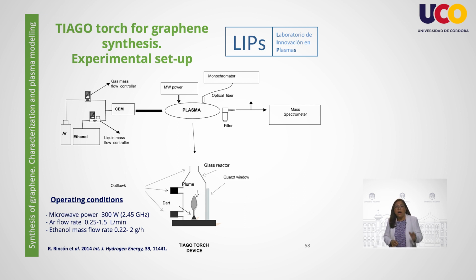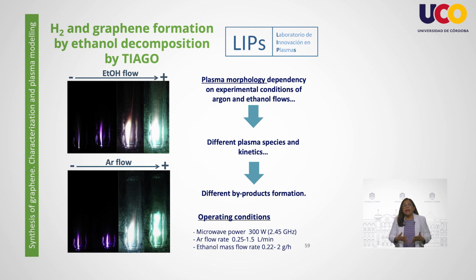Specifically for the graphene synthesis, argon is injected into the Tiago and ionized through the microwaves. Separately, ethanol is heated up with a controlled evaporator mixer before being injected into the process. Once the plasma is stable, ethanol is injected. Now, with this slide, let's visualize the decomposition of ethanol in the plasma system with the operating conditions described in the previous slide. As can be seen in the pictures, the flame size increases as the flow rate increases. The color and morphology of the plasma are already indicating the influence of the operating conditions. Now, we will continue the analysis of this effect on the plasma species and kinetics, as well as the product's formation.